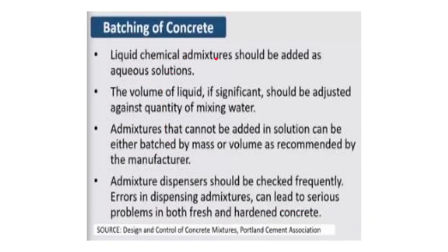The liquid chemical admixture should be added as aqueous solutions. The volume of liquid, if significant, should be adjusted against the quantity of mixing water. Admixtures that cannot be added in solution can be batched either by mass or volume as recommended by the manufacturer. Admixture dispensers should be checked frequently. Errors in dispensing admixtures can lead to serious problems in both fresh and hardened concrete.